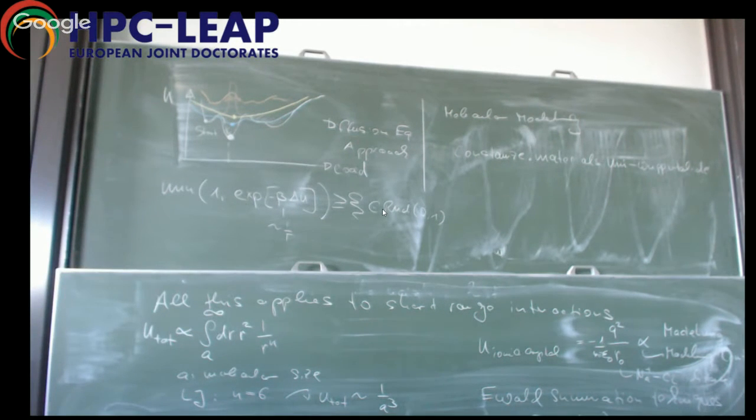People have developed techniques for this to get out reasonable numbers, but there are, in my opinion, good approaches for these things that you can carry out in equilibrium, where you are always a bit on the safe side. Like the Einstein relation for the diffusion coefficient, there is another relation, which is called a Green-Kubo relation. It calculates the diffusion coefficient on the basis of the velocity-velocity autocorrelation function. And you can do this for other transport coefficients as well.